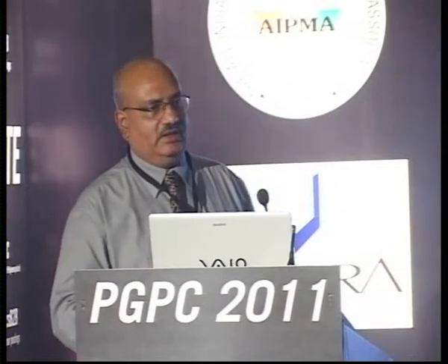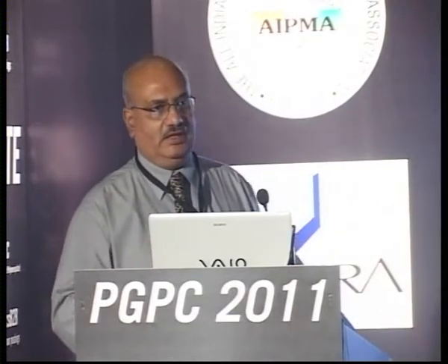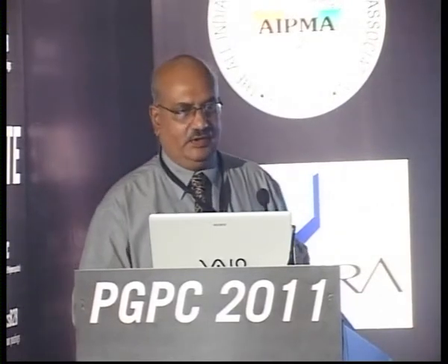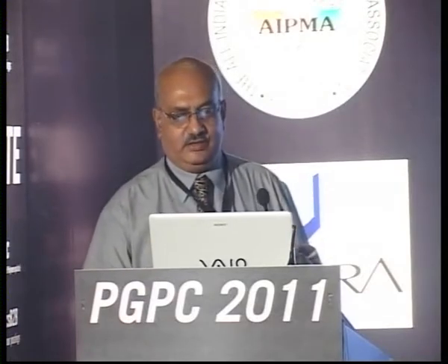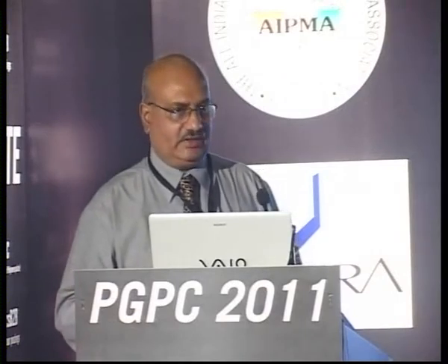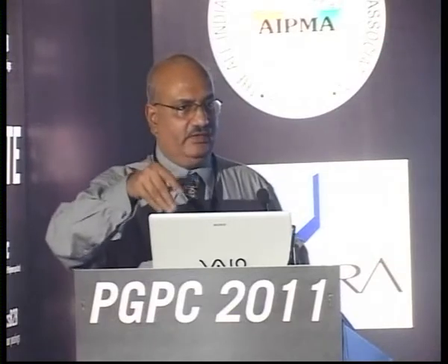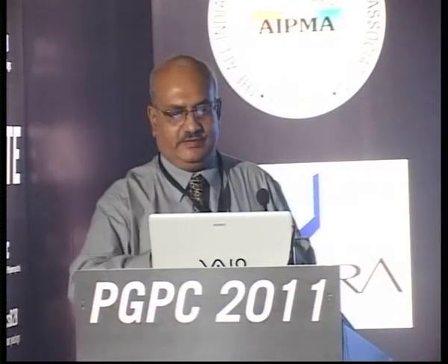An unfilled material and a filled material require different loading of pigments to achieve the same color. So unless we know exactly what kind of filler is there in your polymer and what is the loading of that filler in the polymeric material, it is difficult to design the loading of the colorants. If you say, give me a 2% master batch, I should know how much additive to put or how much colorant to put in the master batch, and that will only come by knowing how much is the loading of fillers and other additives in the base polymer.